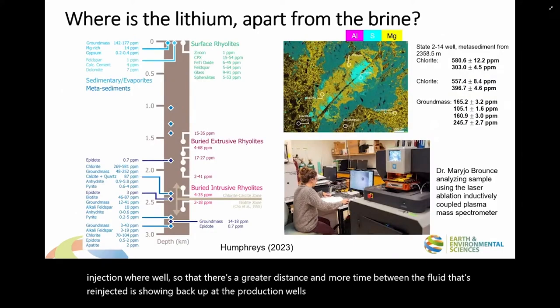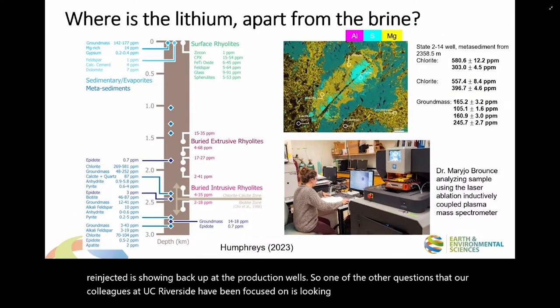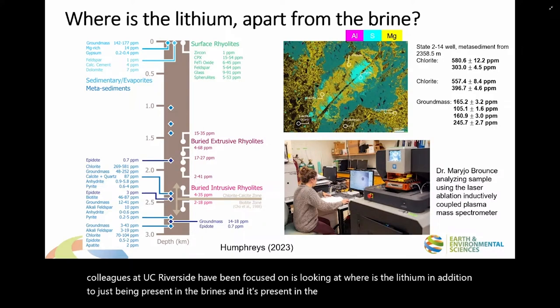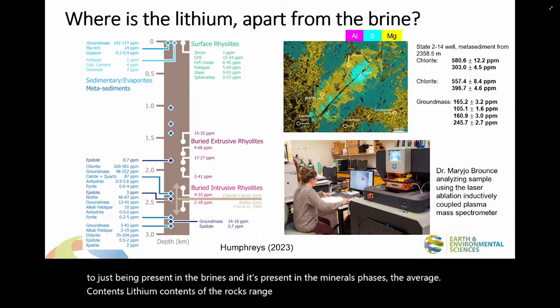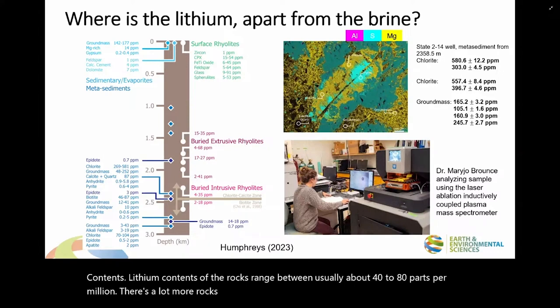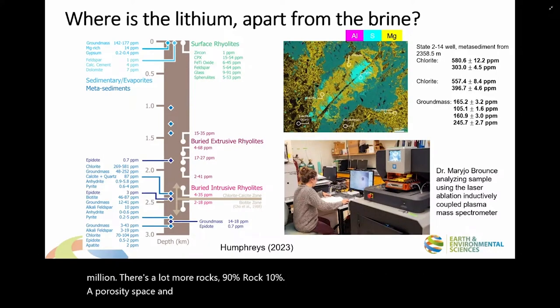So one of the other questions that our colleagues at UC Riverside have been focused on is looking at where the lithium is in the brines, and it's present in the mineral phases. The average lithium contents of the rocks range between usually about 40 to 80 parts per million. There's a lot more rock, 90% rock, 10% porosity space. And so that adds up to a lot of potential lithium that could potentially recharge this system.